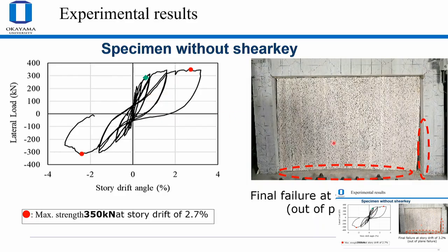More than half of the strength is carried by the CLT walls. At the end, at 3.2, which is a very large drift, it actually failed out of plane. It went like this, outside. But when I released the load, it returned back. We stopped loading at that point and considered that it had already failed. If you see here, there are a lot of gaps here and here. We are pushing in this direction, so this is attached because the strut is in this way, and here are the gaps. So this is without shear keys.